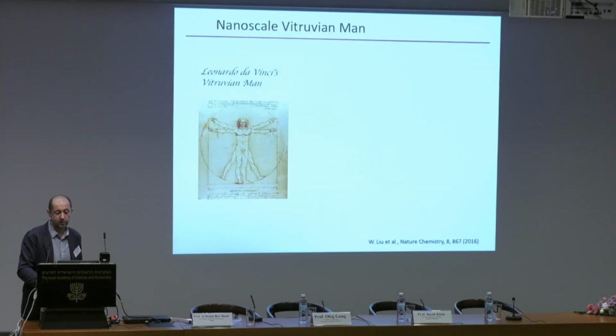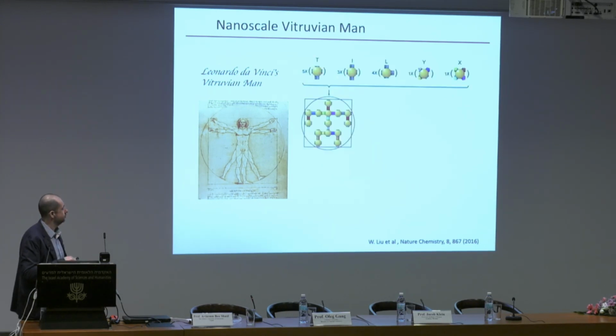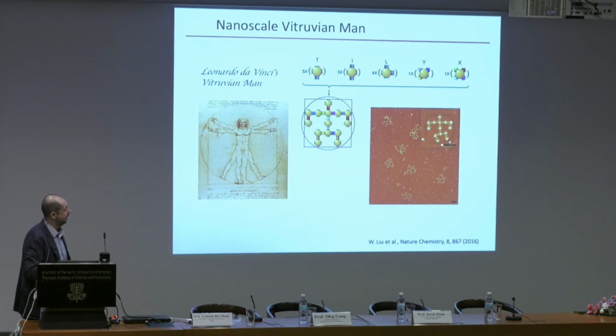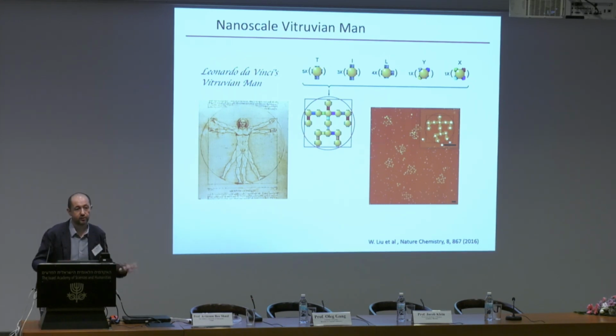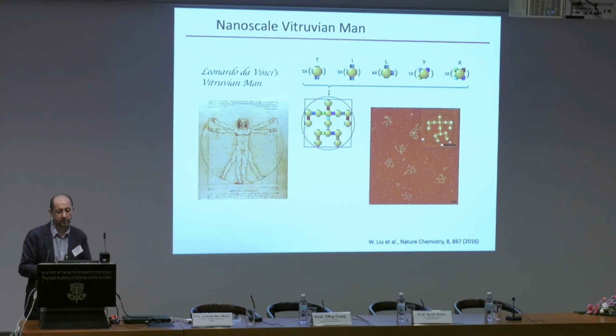In something much more complicated, like Leonardo da Vinci's Vitruvian Man, an implementation at the nanoscale can be done. Again, this is a low resolution, but in this case, we're able to use these 14 components and mix them in the stoichiometry ratio which corresponds to this low-resolution design, which led us to the formation of this type of architecture simply by mixing those components with prescribed structure. I want to stress the yield is very low, 5–6%, but again, it's significantly higher than the yield of producing a human.